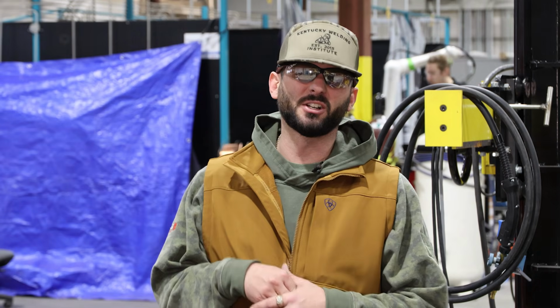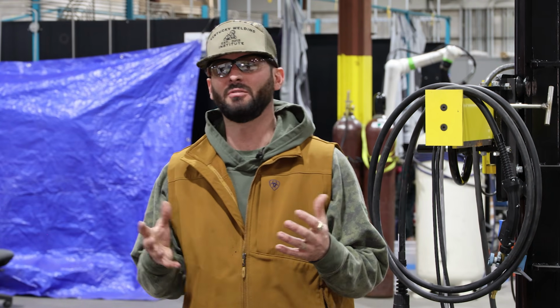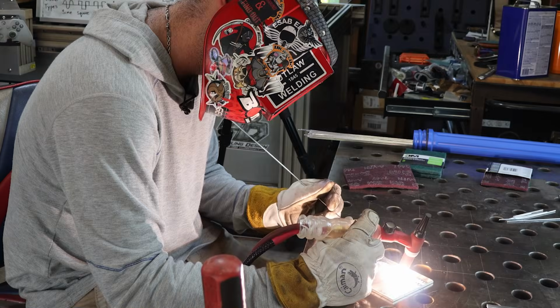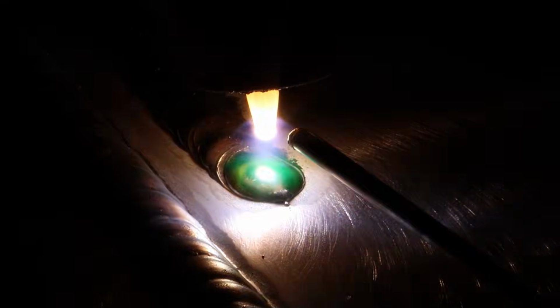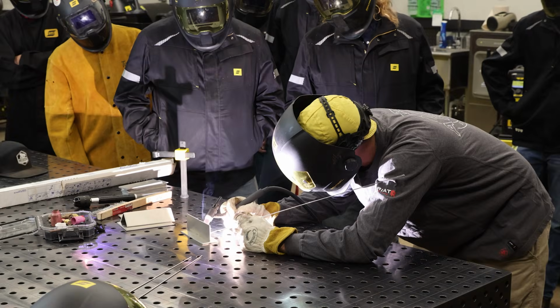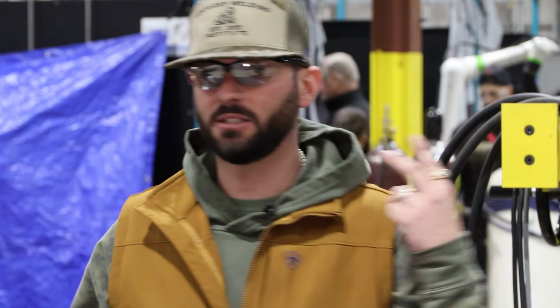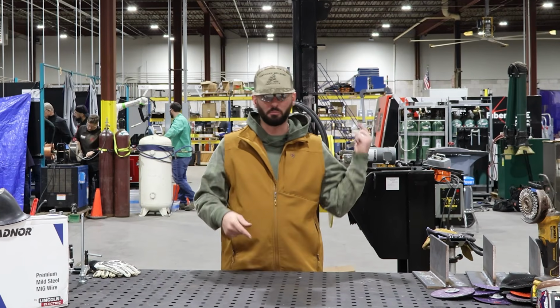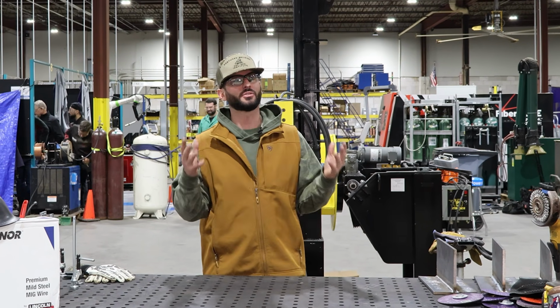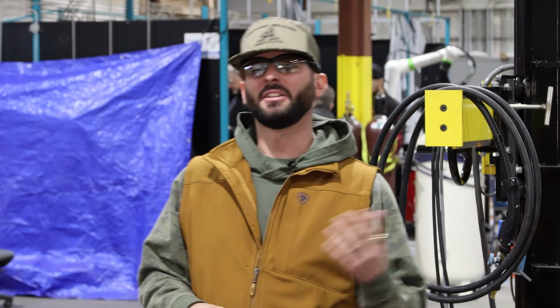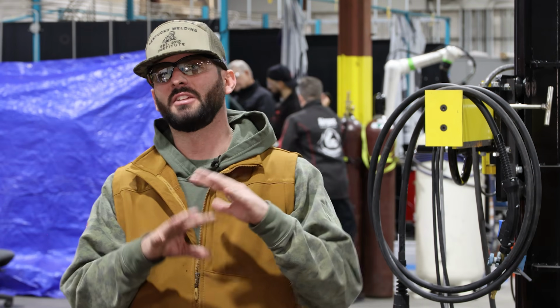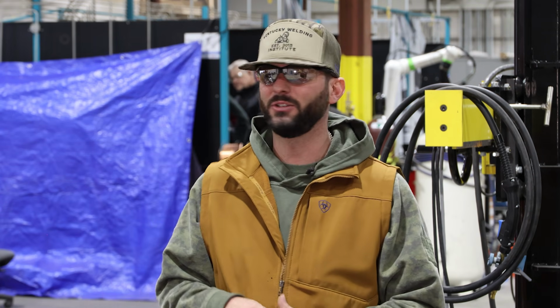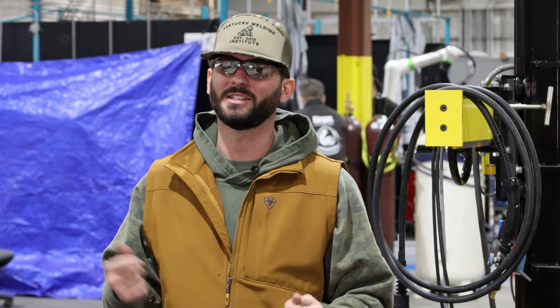Now, when it comes to the gas tungsten arc welding process, or TIG welding, which is probably one of my personal favorite processes, I've really only used 100% argon. While I have seen some helium being mixed in to TIG weld some of those thicker aluminum pieces of material, I've used 100% argon when TIG welding carbon steels, stainless steels, 9 chrome, duplex, Inconel, titanium, aluminum, brass, copper. You can TIG weld so much with just 100% argon. I think that's probably why I like TIG welding so much. Outside of the aesthetically pleasing welds that it makes, you can pretty much weld any metal with just the right gas and right filler metal.